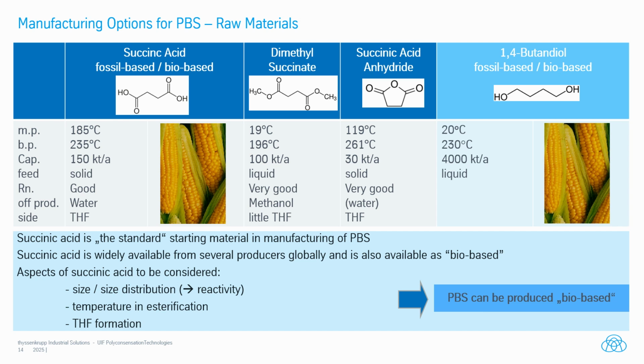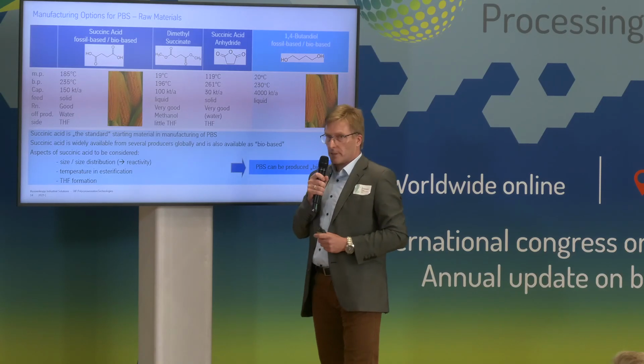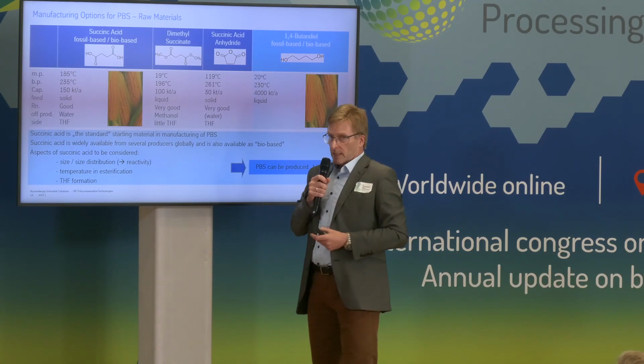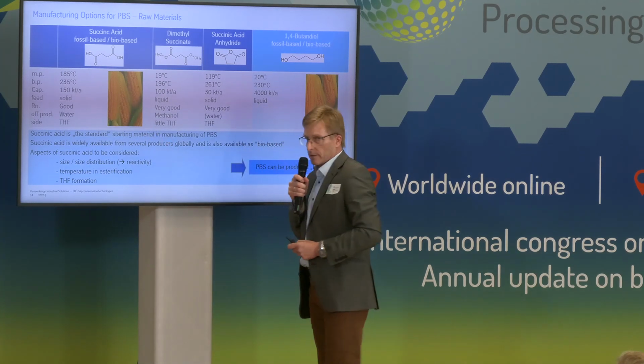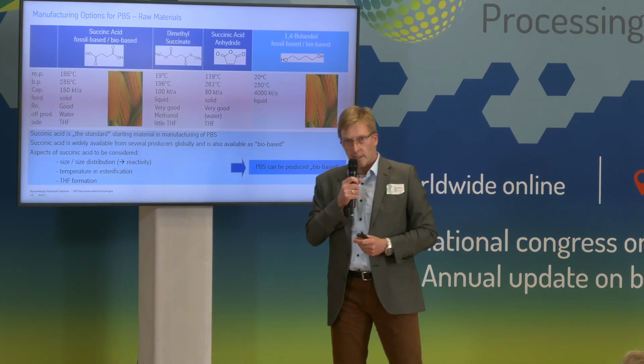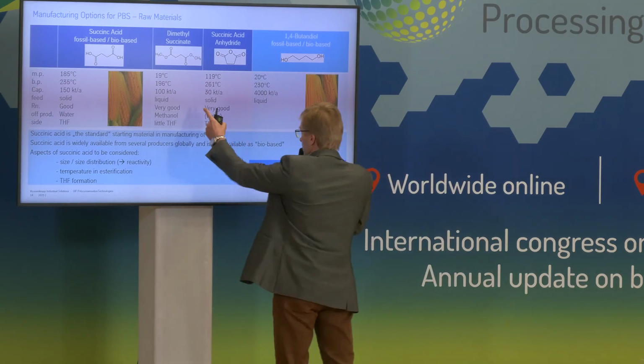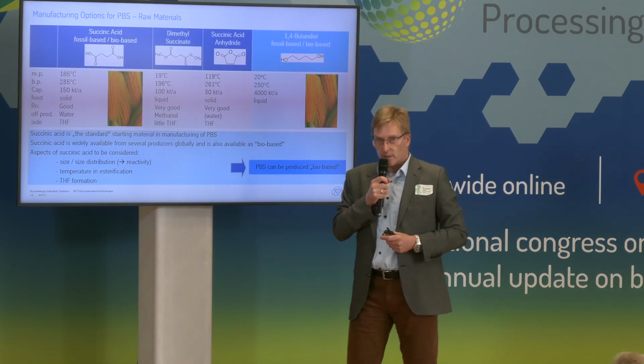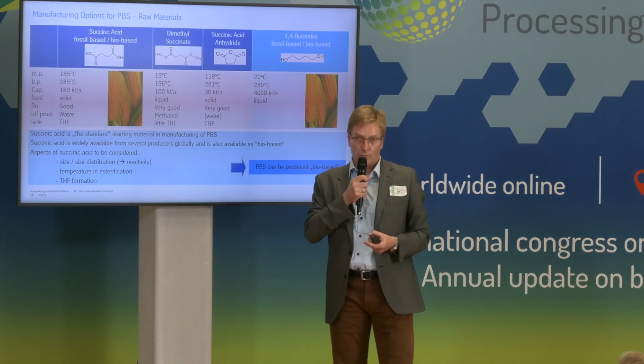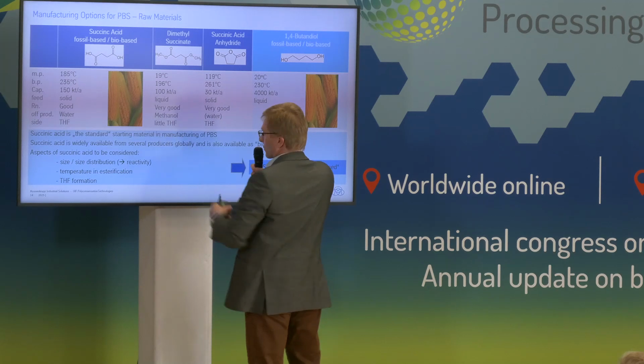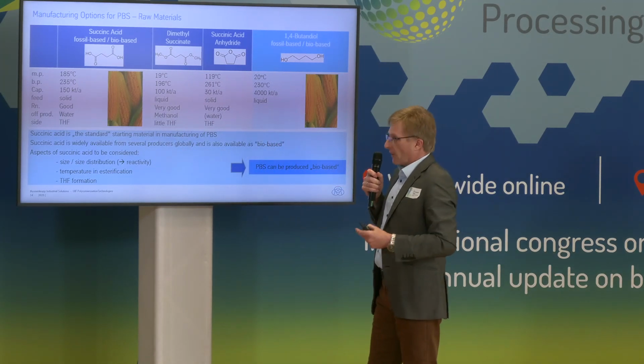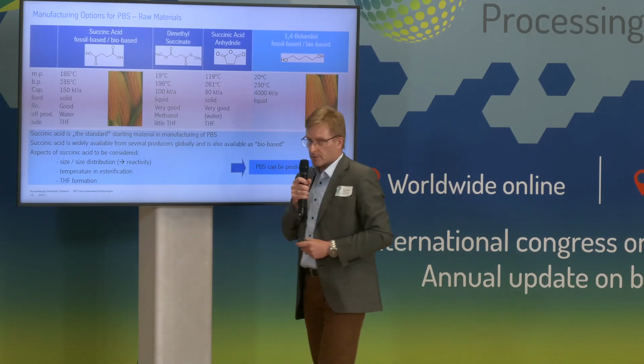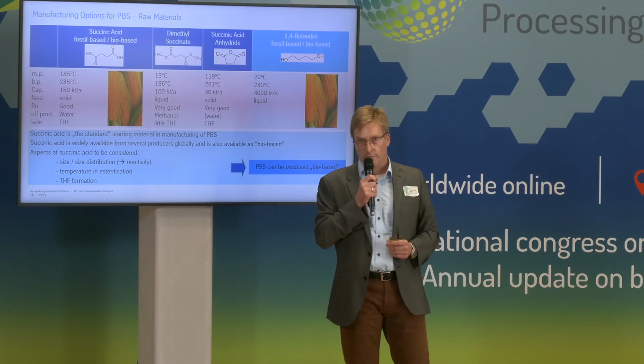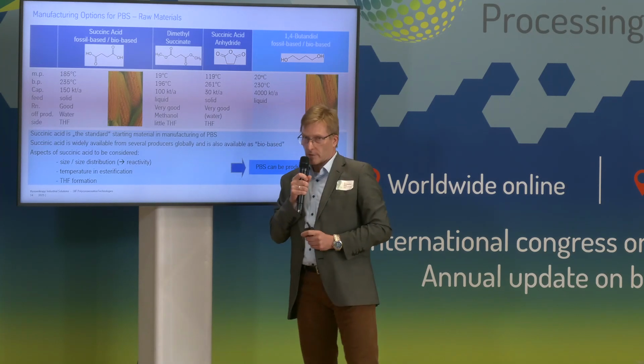The difference might be, if you start out with succinic acid, we see, I would not say disadvantages, but it's a little bit more challenging, for example, than if you would start from DMS for making PBS. The succinic acid does have quite a high melting point of 185 degrees. This means we must run the esterification under much higher temperatures than we would run a trans-esterification with DMS. Also the DMS comes typically as a liquid, which makes feeding into a process much more simple than if we have to feed a solid substance like the succinic acid. And finally, because of the high acidity of the succinic acid, you are generating much more THF in the esterification than what you produce in the trans-esterification of DMS.